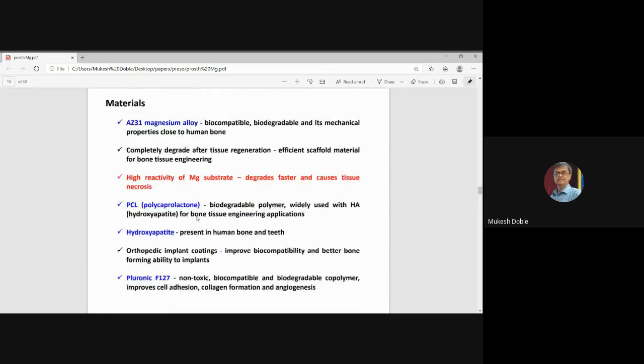So we looked at AZ31 magnesium alloy, which is biocompatible, biodegradable, with mechanical properties much less than titanium and stainless steel, closer to the bone. It can degrade after tissue regeneration. So finally, you are not going to have the metal inside, unlike titanium or stainless steel. Then the one problem with magnesium is it can degrade very fast. So what we did was we coated the magnesium surface with polycaprolactone. It's an FDA approved polymer. It doesn't biodegrade fast, unlike polylactic acid or polyglycolic acid and so on, but it slowly degrades over a much longer period.